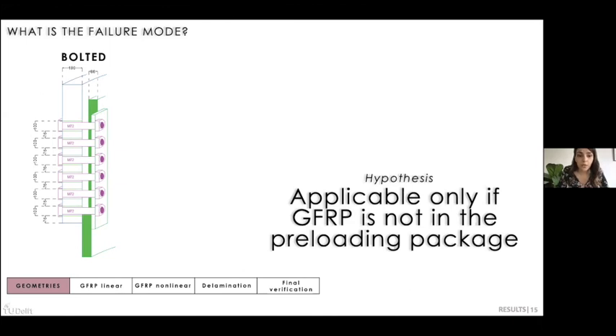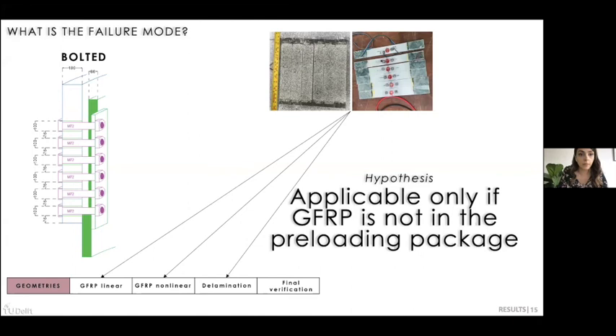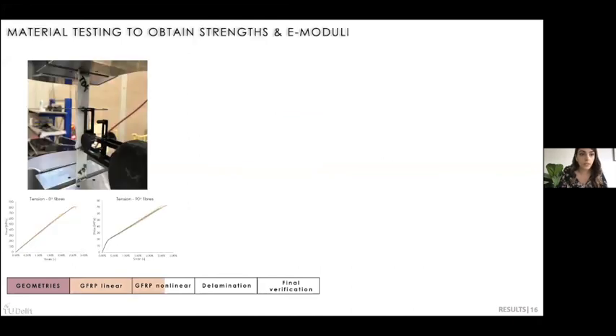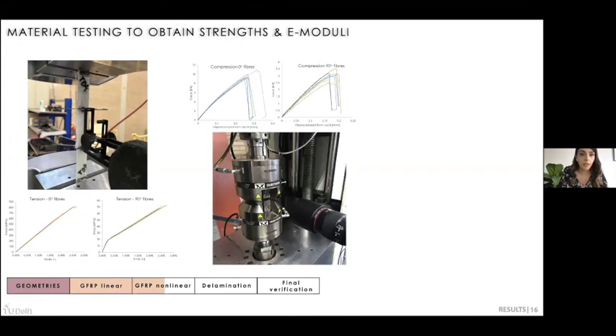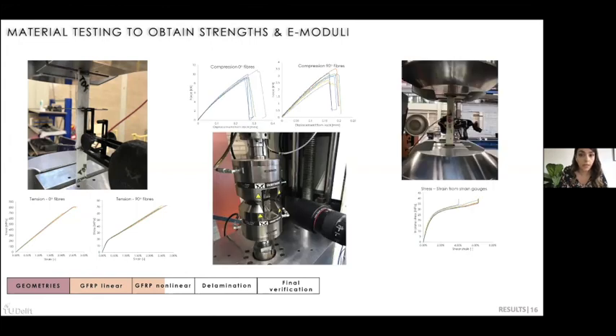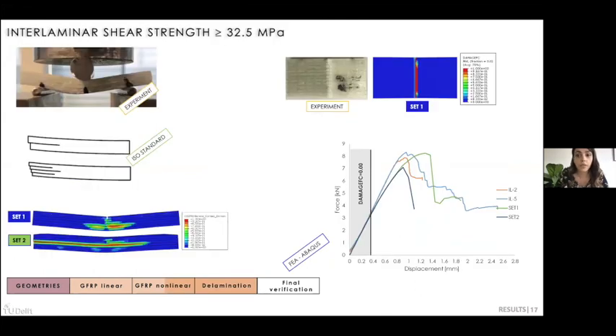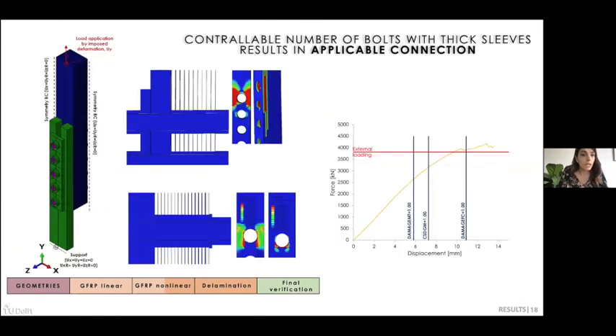So I had to input the correct properties for the GFRP material and for its delamination. So once again, I used experiments. I did coupon level material tests based on ISO standards. You can see here the tensile experiments that I did, the compression tests, and the in-plane shear tests. And of course, I also did the 3-point bending experiment to quantify the interlaminar shear strength, which is the strength that leads to delamination of a laminate. I also made a finite element model for that to make sure that I use the correct input values. And then once again, I had everything for my final verification.